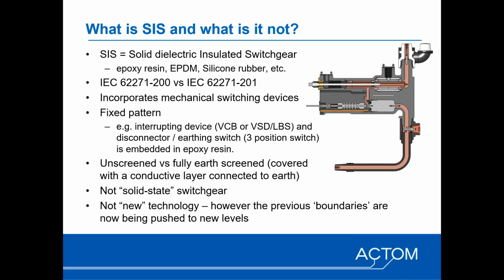The other thing to note is that solid dielectric switchgear incorporates mechanical switching devices, so it does not mean that it uses solid state. A lot of people initially assume when we talk about solid dielectric that it might imply solid state switchgear, and that's not the case. Solid dielectric insulation effectively refers to the insulating medium, not the type of interrupting medium, as covered earlier. So you would typically have an interrupting device, which could be a vacuum circuit breaker, a vacuum switch disconnector, or a load break switch, as commonly used in the US terminology, as well as a 3-position disconnector, all embedded in epoxy resin, and then, as we'll talk about later, covered by an earthed conductive screen.